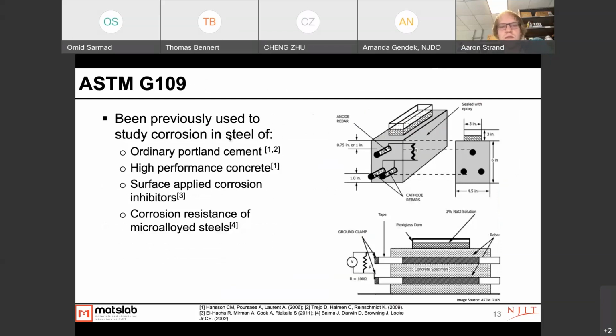So ASTM G109 has been previously used to study corrosion in steel in ordinary Portland cement and also high performance concrete. It's typically been used for surface applied corrosion inhibitors. It's also been used to look at the corrosion resistance of microalloyed steels. In this test method, there are 3 different bars of reinforcement embedded into the beam, 2 cathode rebar on the bottom, and one single anode rebar on the top. And there's a resistor placed between them to create the cell. The de-icing, or chloride brine, is ponded inside of the dam on the top of it. The sides and top outside of the dam are coated with epoxy, so the bottom is left freely exposed to the air.